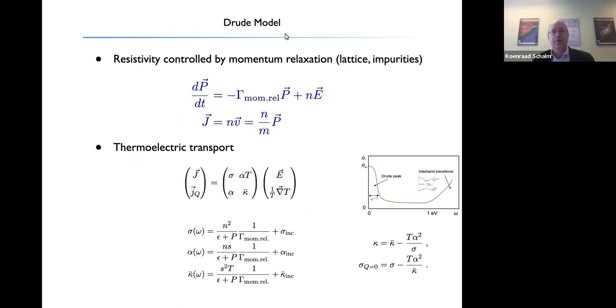Now, to describe this, let us briefly review what is the dominant contribution to the resistivity in ordinary metals, or even, as we believe, in strange metals. The resistivity in ordinary systems is controlled by momentum relaxation. And this momentum relaxation can arise either from the lattice itself or from impurities. There's a very simple model, the Drude model, already a century old, which captures this result. You simply say that the momentum relaxes with a certain rate, but at the same time it's accelerated by an electric field, so the momentum of each single electron. And then you simply say that the current in the system is proportional to the velocity, or in other words, the momentum divided by m.